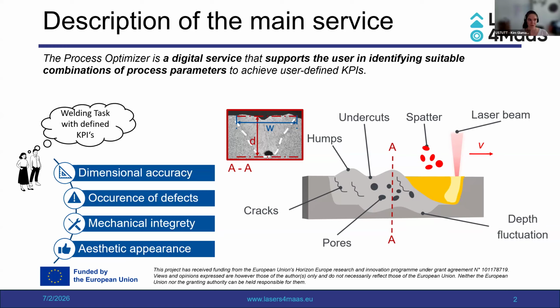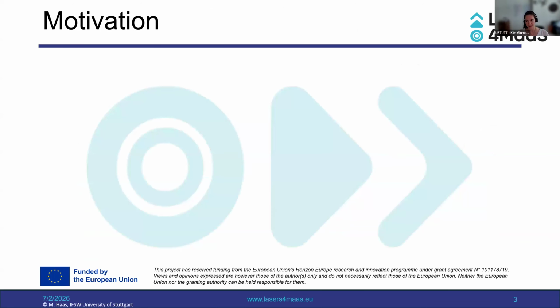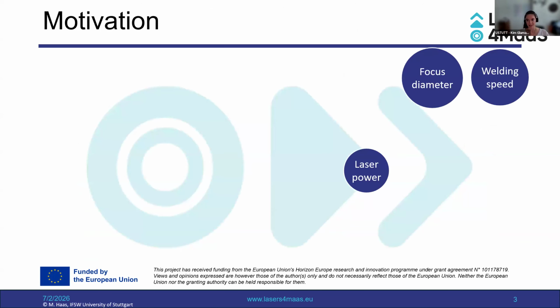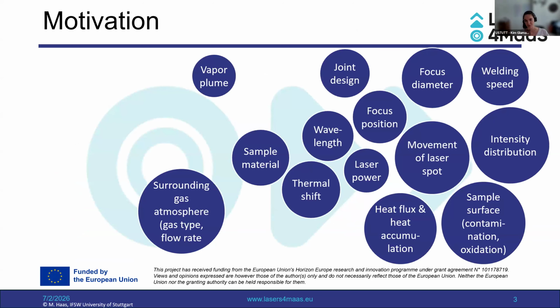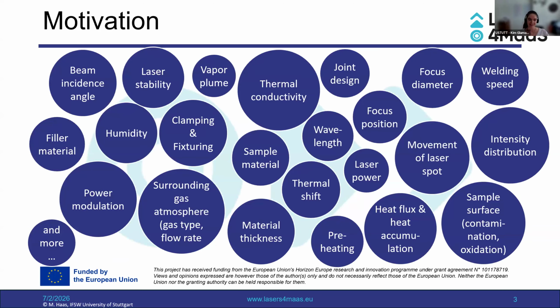As probably most of you know, we have quite a lot of influencing factors on the productivity and cost of the weld seam, but of course also on the quality. For example, the laser power, the welding speed, the focus diameter, intensity distribution, and many more. And in the Lasers4MaaS project, as Pasquale also said, we are working with dynamic beam shaping, so we add even more parameters to that already large parameter space.